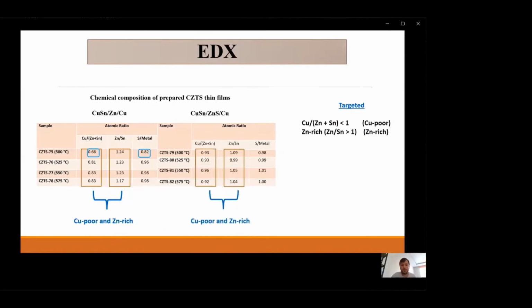And also for B-type samples, you can see all of the samples have a copper-poor and zinc-rich composition except this sample. And in this sample, you can see the zinc ratio is the stoichiometric ratio. So maybe it can be excluded due to this composition.